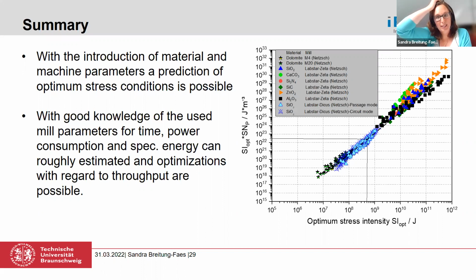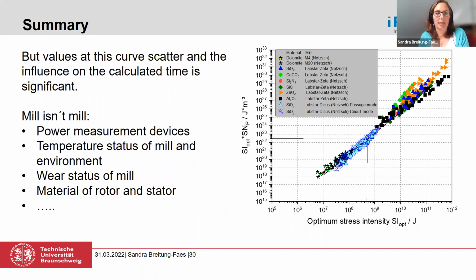After running the discus experiments, I included these values here as well, just to show you that this idea of introducing the residence time instead of the grinding time to the stress number was a good one, because the correlation is very fine for the circuit mode as well as for the passage mode, which you can see here for the two blue data points. But at least these values scatter a lot, especially here above. So one has to be a little bit careful.